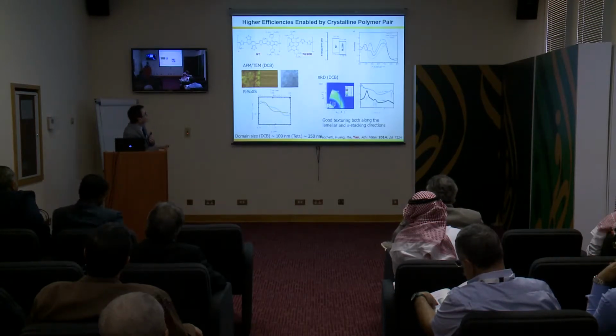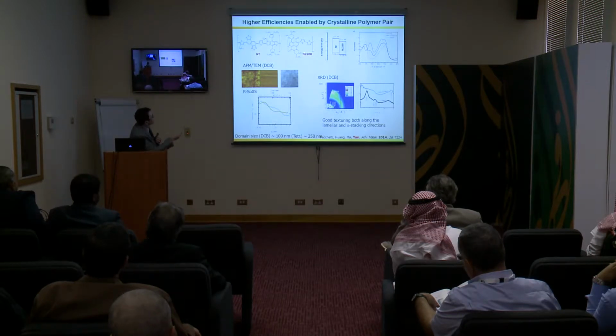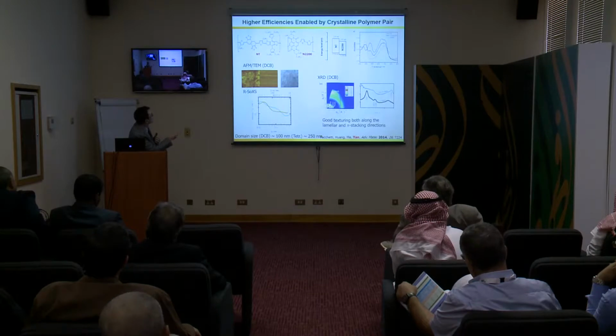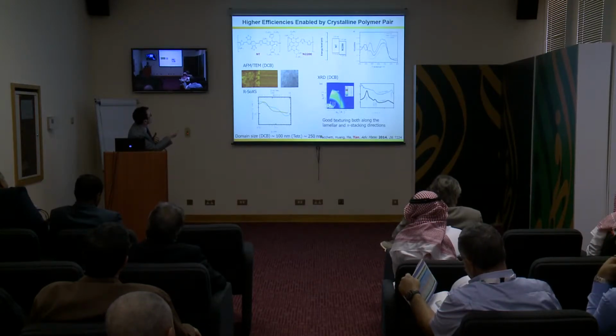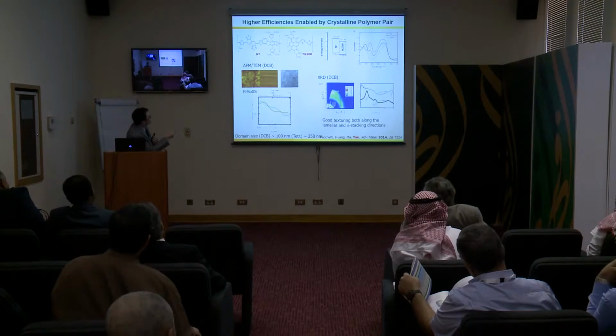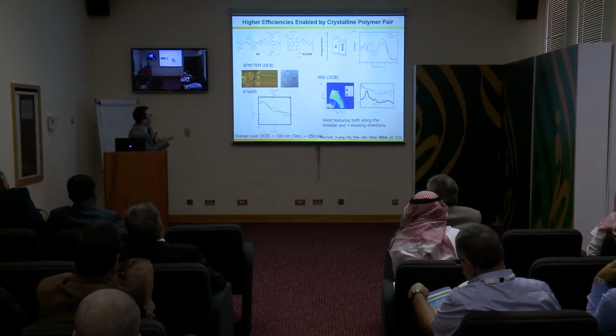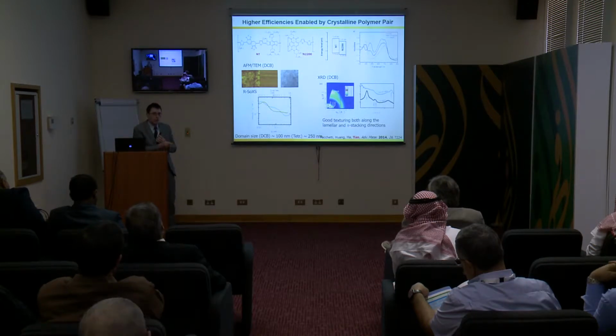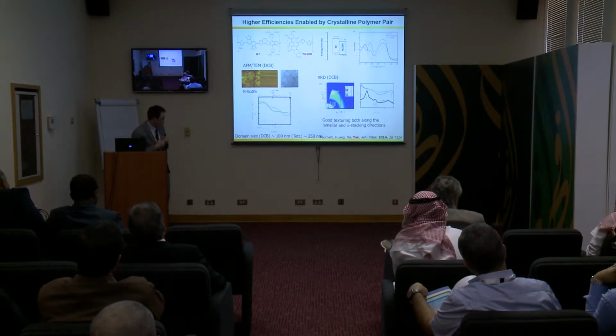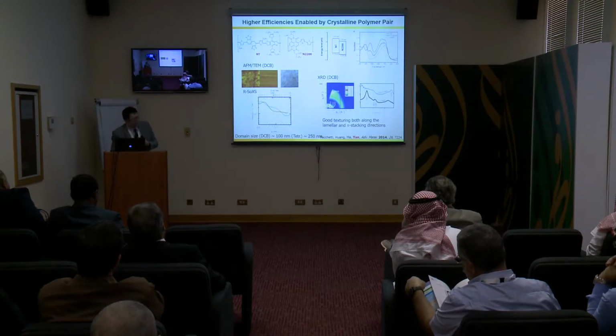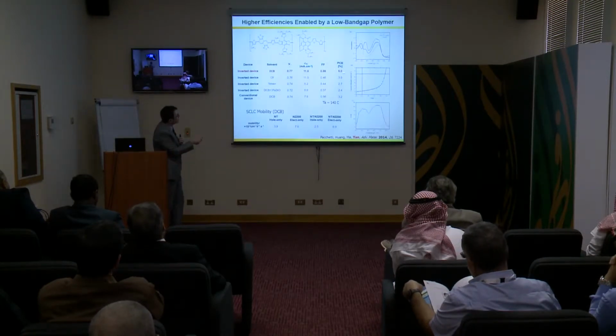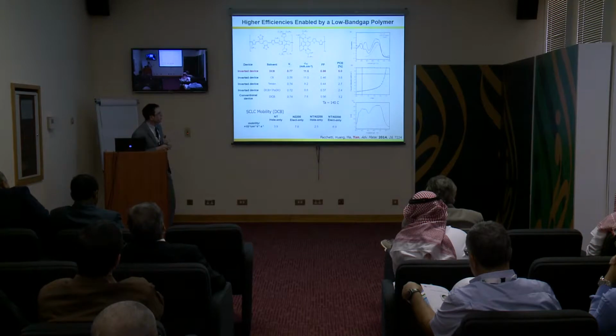More recently, we found a little better combination by using, again, as a polymeric acceptor, this naphthalene diimide polymer. It was a new polymer developed at University of Hong Kong. When we use this polymer, we create blends where the domain size is not optimal. It's still quite large, on the order of 100 nanometers, so it's not as small as we want. But this film remains quite crystalline upon blending, and we can start getting optimized efficiency on the order of 5%, which is still far behind what we know for fullerenes, but they're becoming more interesting.